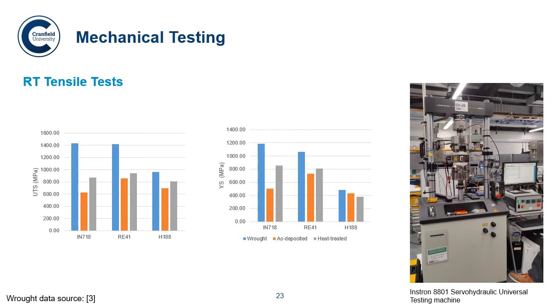So then we did our mechanical testing. We did room temperature tensile tests. As you can see from the graphs, in blue you can see the wrought strength, which is the data from literature, and in orange we have as deposited. That's material that was just extracted and didn't undergo any heat treatment.